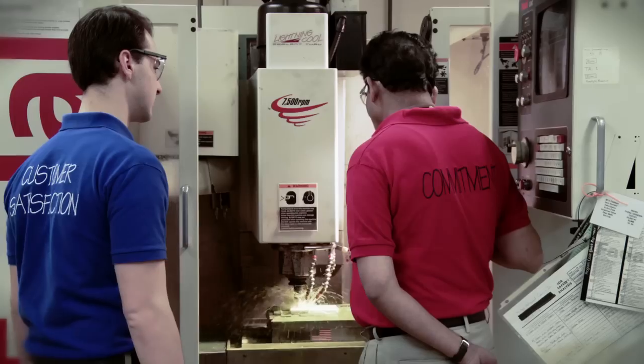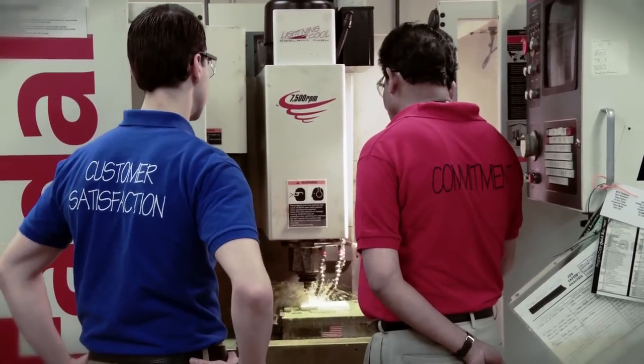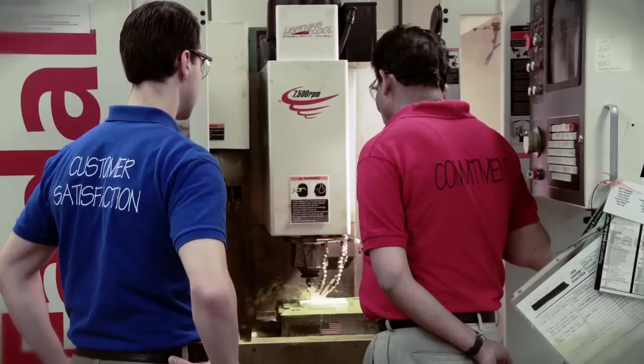For a one inch drill size, a spindle speed of 100 revolutions per minute is suggested at a feed rate of 12 thousandths of an inch per revolution.